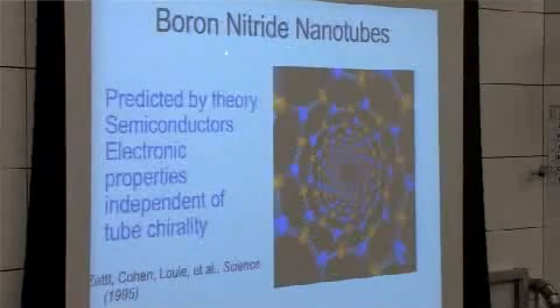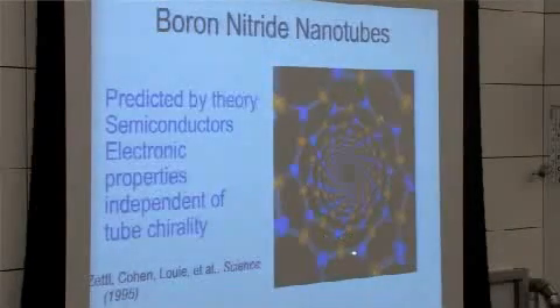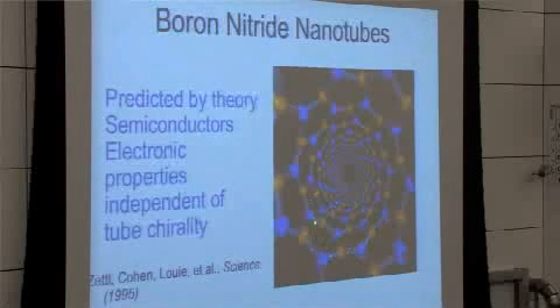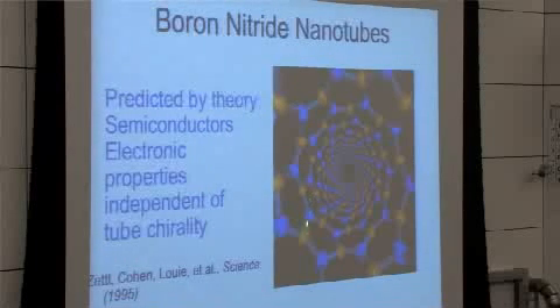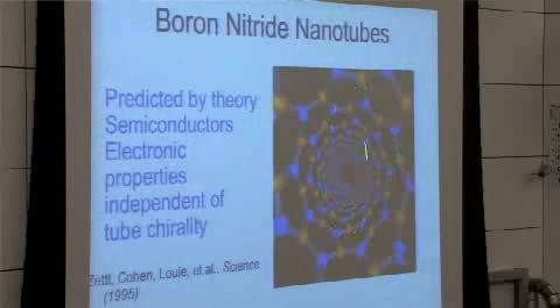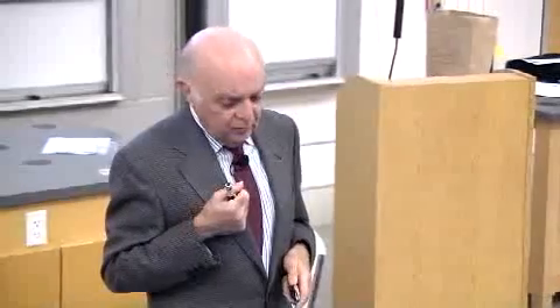On the computer, first calculation, then a computer, we were able to construct a boron nitride nanotube. These are very different from the carbon nanotubes, but they're about the same size. Instead of having carbon, carbon, carbon, carbon, these are boron, nitrogen, boron, nitrogen. And the wonderful thing about these tubes is that if you put a little carbon in them, if you dope them, the electrons travel right down the center of the tube. And you can apply them for many applications. So this area has been moving along at a very fast clip.